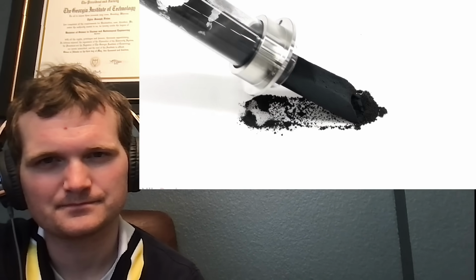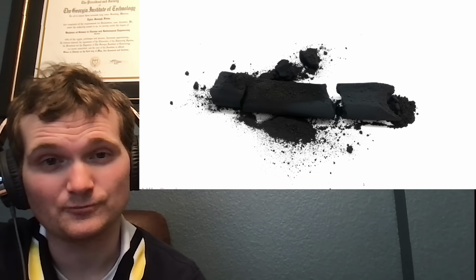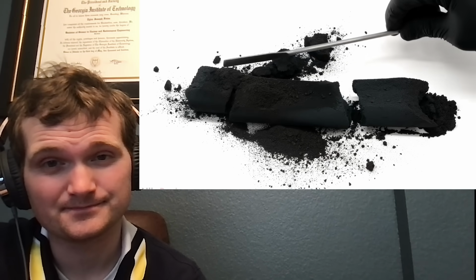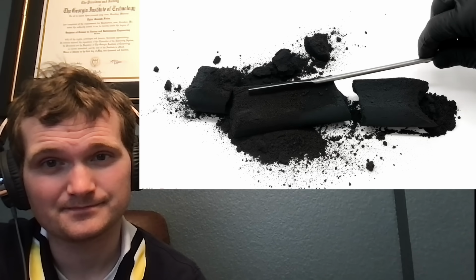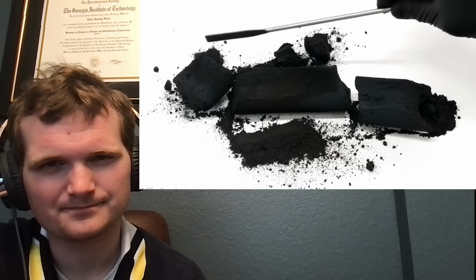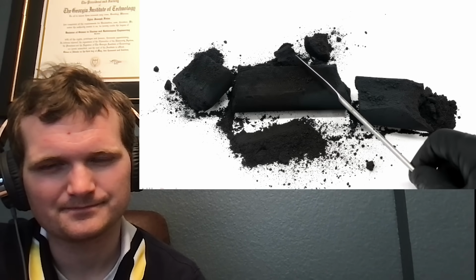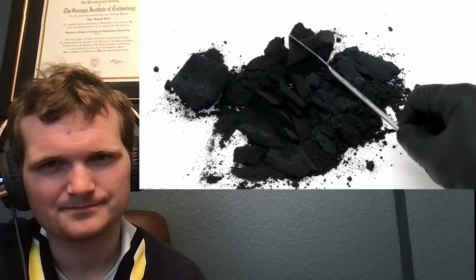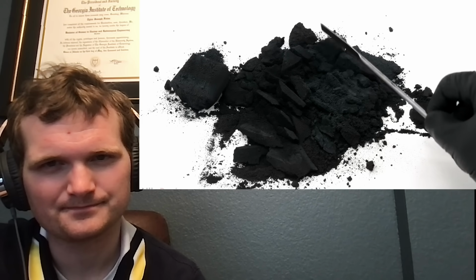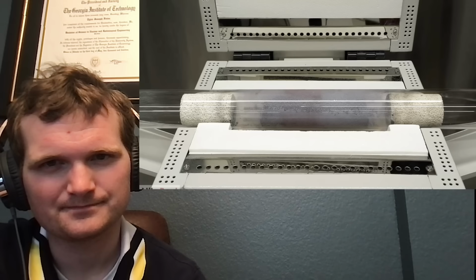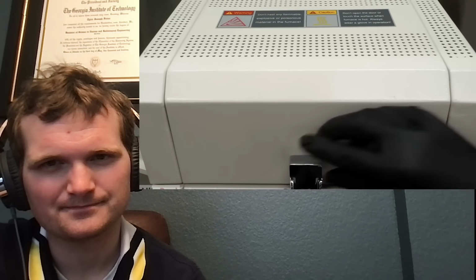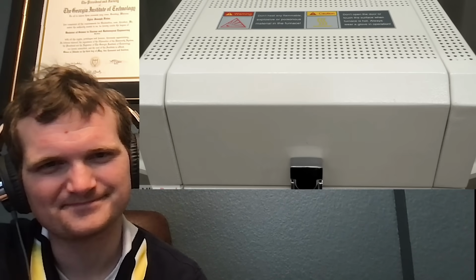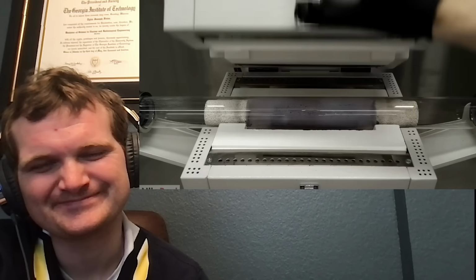When it was done, I dumped it all out, and it was definitely a lot blacker than it was before. Wow. However, it looked like it still had some unreacted brown stuff in it. When I crushed it up, it looked okay, but I didn't like this at all, and I decided to run it again. I put it all back into the furnace, and I ran it for another 28 hours, and this time it was much better.